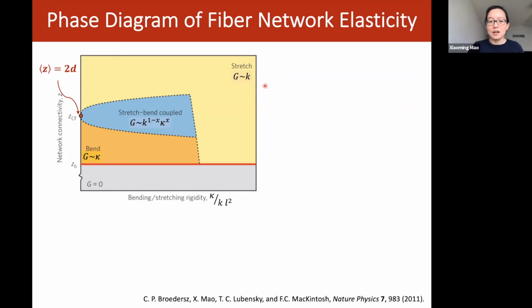And it's large. Below this point, the network is connected, but it doesn't have rigidity in the central force limit. So it needs additional interactions, such as the bending stiffness of the fibers, to give it an elastic modulus. So you only have elasticity when you turn on bending stiffness. The shear modulus is proportional to the bending stiffness of the fibers. So the elastic modulus is much smaller here in the bending dominated regime than in the stretching dominated regime.